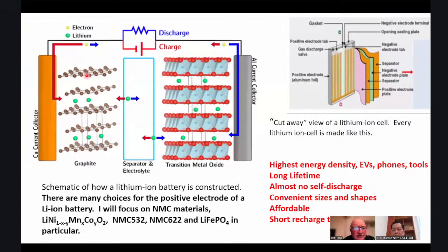So this type of battery is very reversible, and one of the reasons is that the materials used as the positive and negative electrode only expand and contract a relatively small amount, maybe 10% for the negative electrode side. When the lithium goes in, it gets a little bit bigger, and when the lithium goes back out, it contracts to its original size. And the transition metal oxide side is a little bit smaller variation, maybe between 3 and 8%, depending on exactly what material is being used.